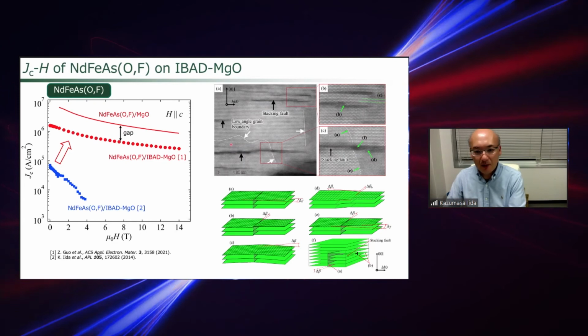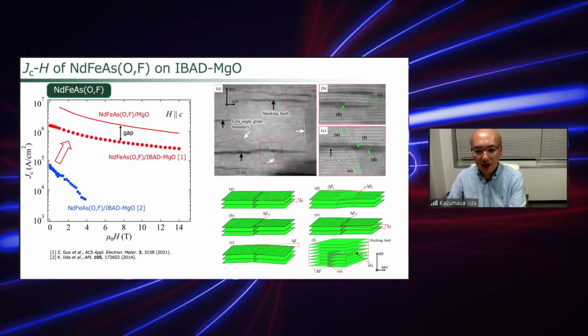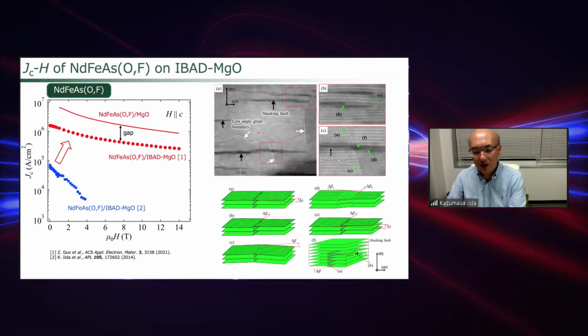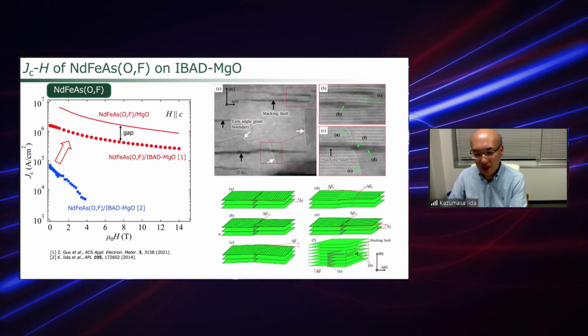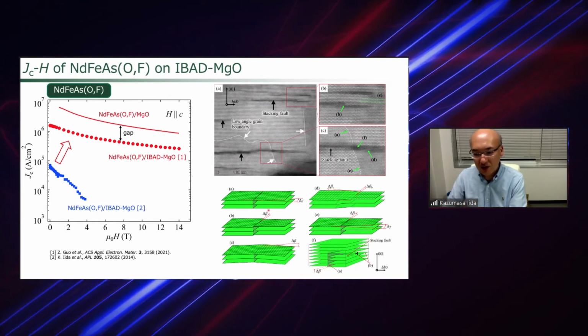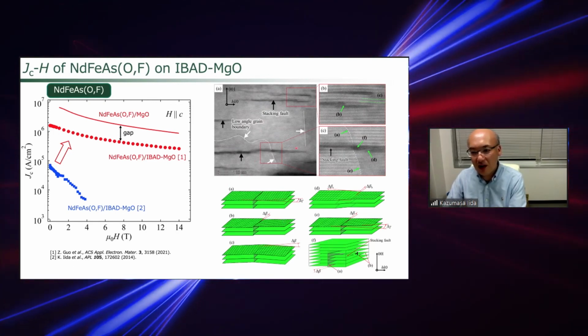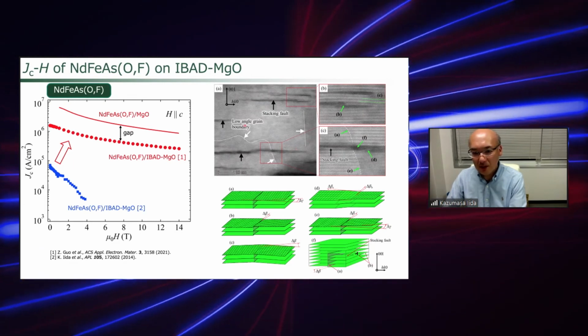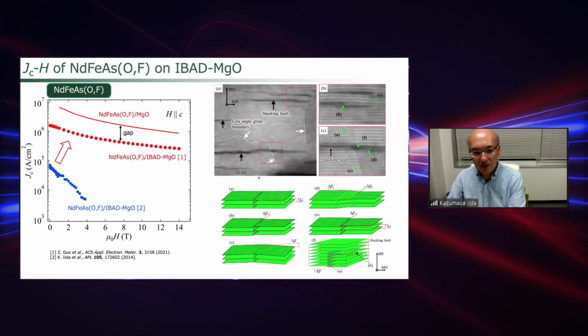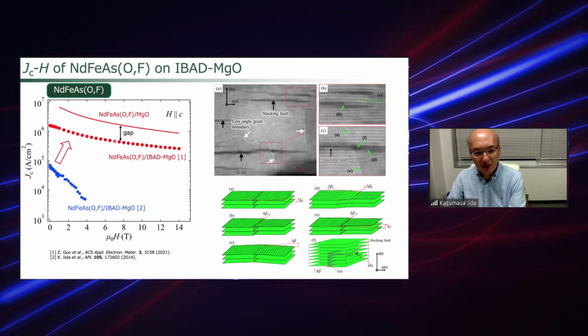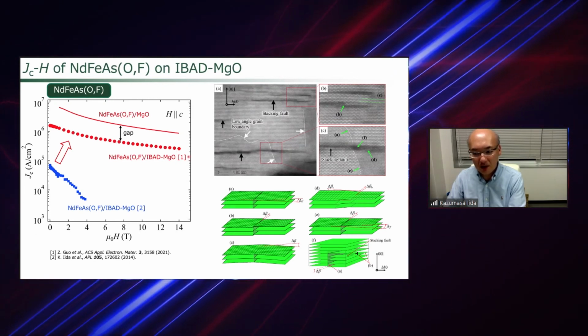And we checked the microstructures of these materials, and we see a lot of defects inside the films. Here is a schematic illustration of the defects present in our films. But nevertheless, these defects work as very strong pinning centers, especially in a magnetic field.